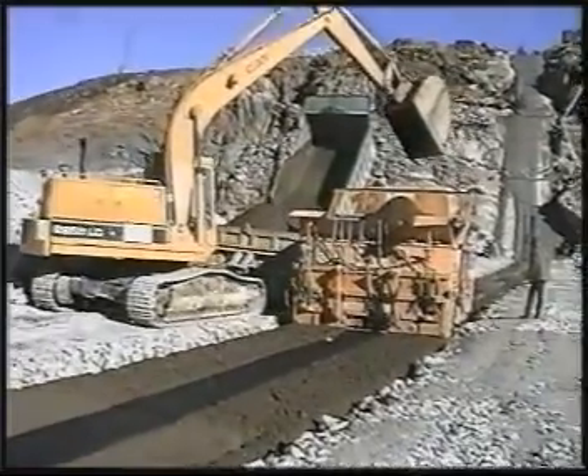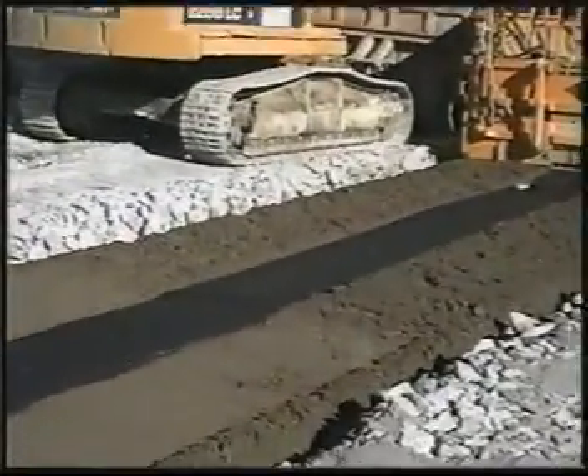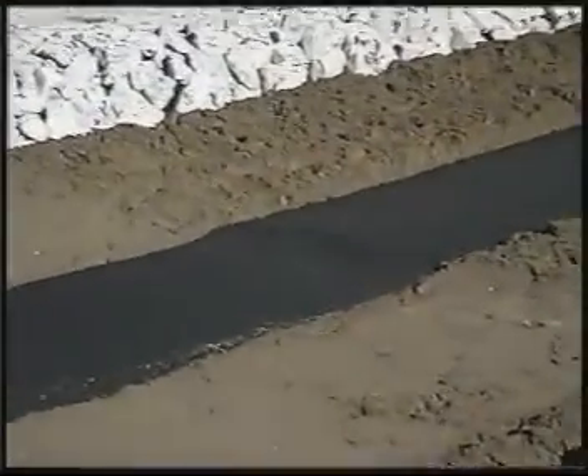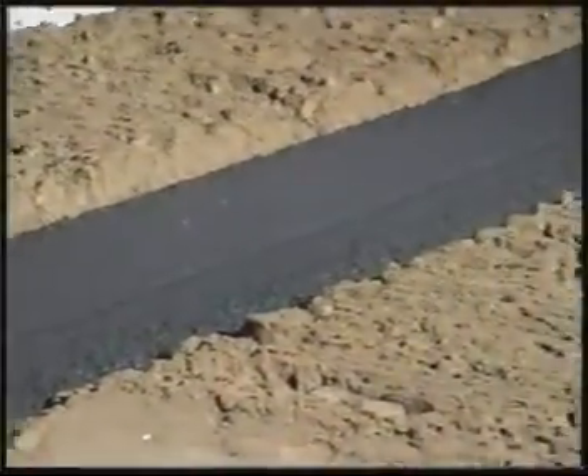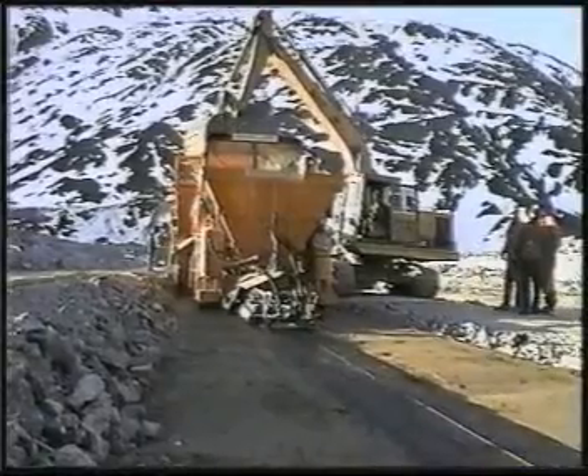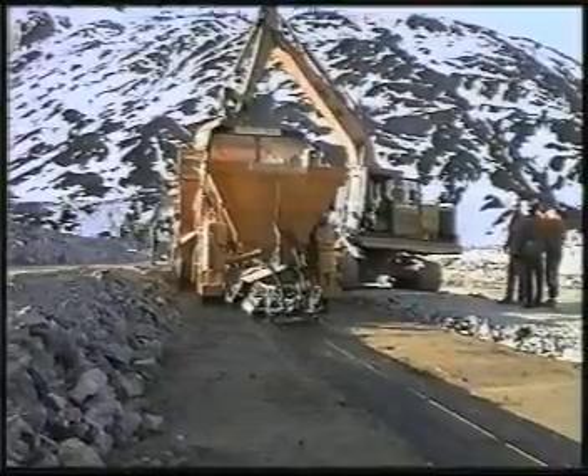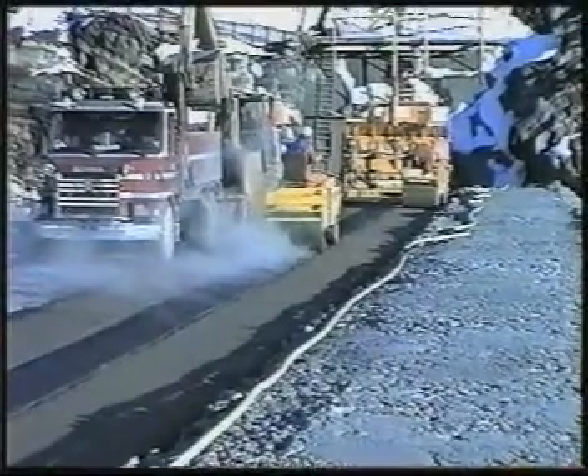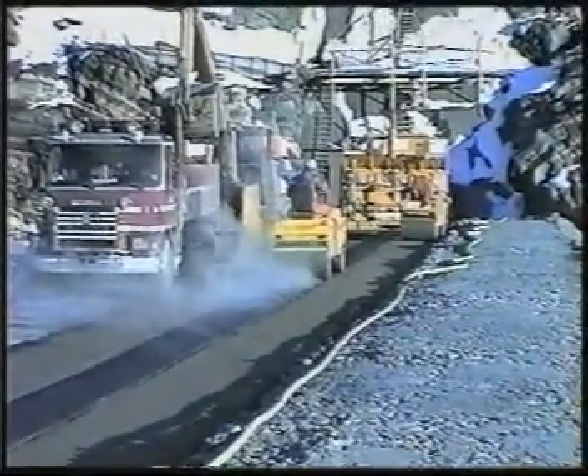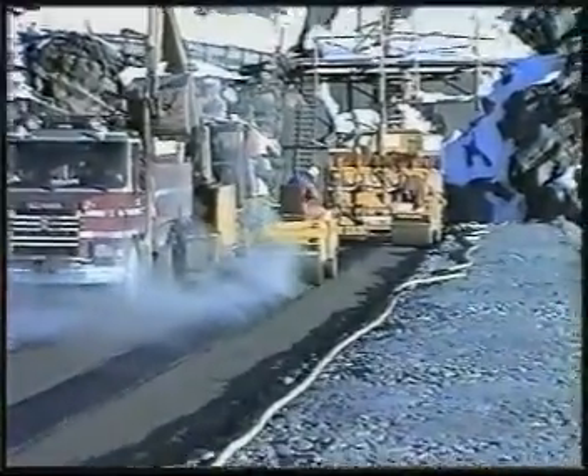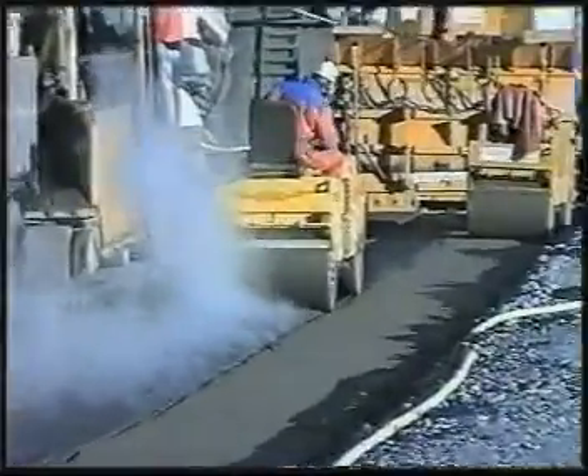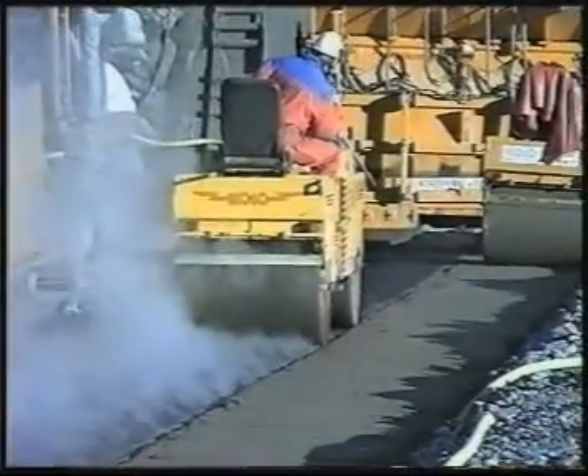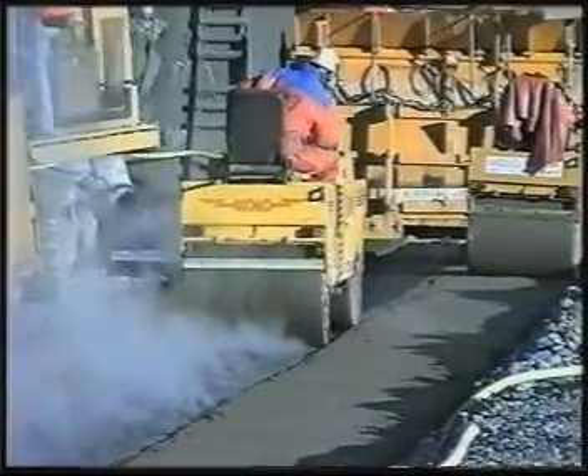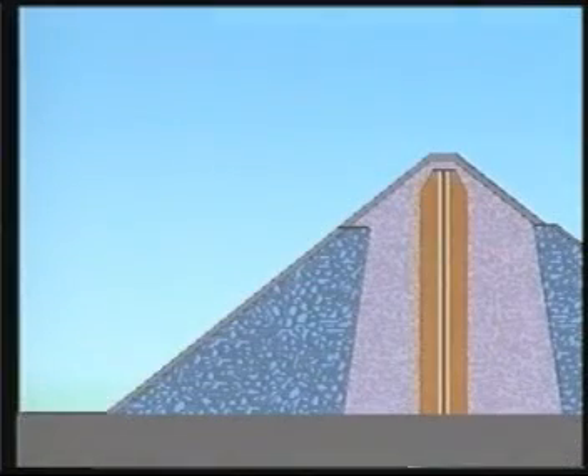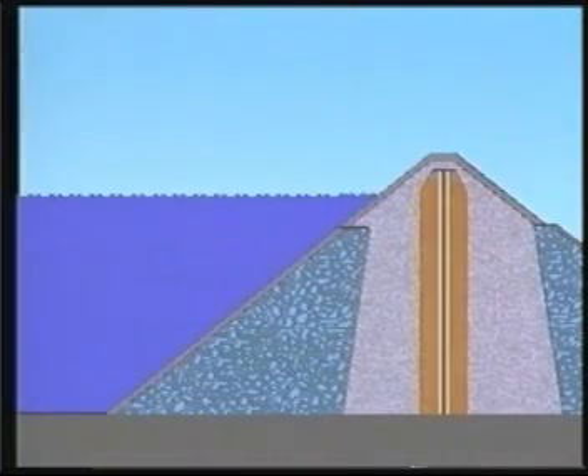Asphalt is an elasto-viscoplastic material which can sustain differential foundation settlements and dam distortions without cracking. Embankment dams with flexible asphalt concrete cores are, due to these quality features, very earthquake resistant. Inside the body of the dam, the asphalt exists under near ideal conditions, and the core will remain as a flexible and impervious membrane. Asphalt will behave as a self-healing material if any movement or cracking should occur.